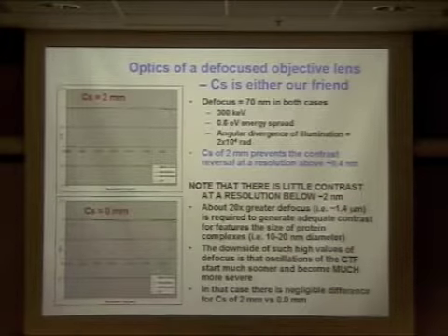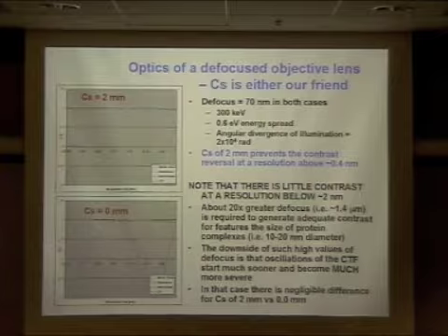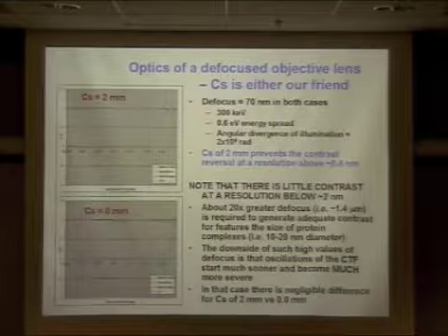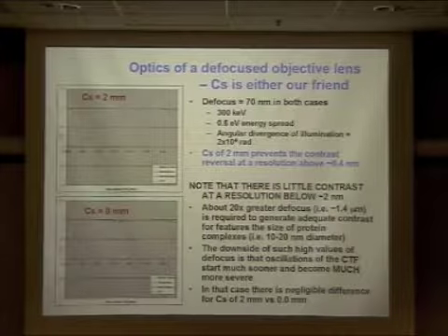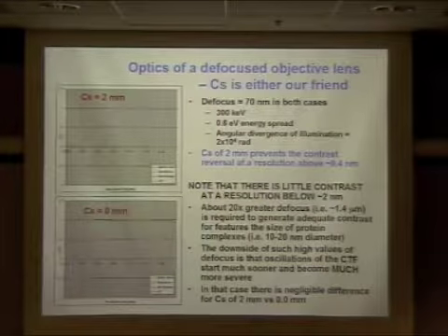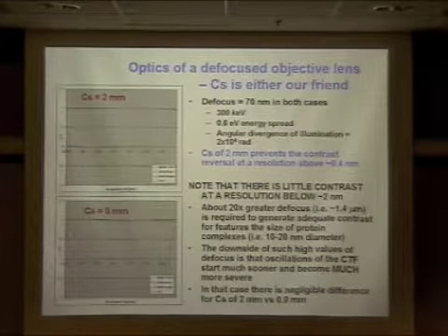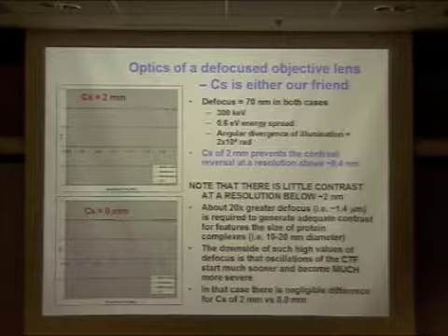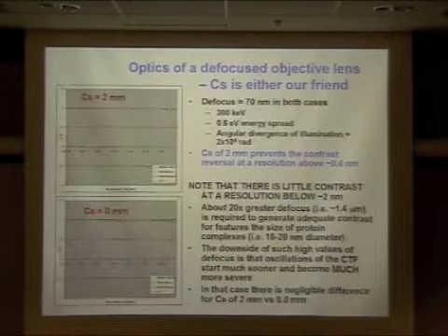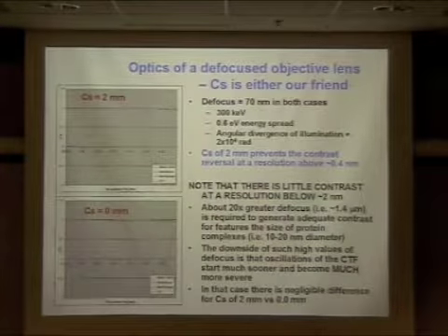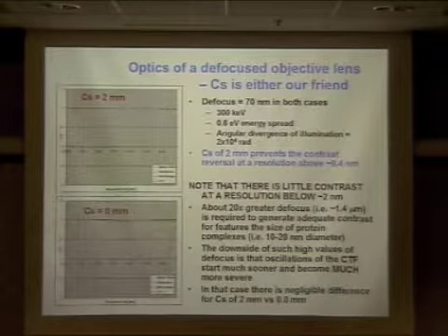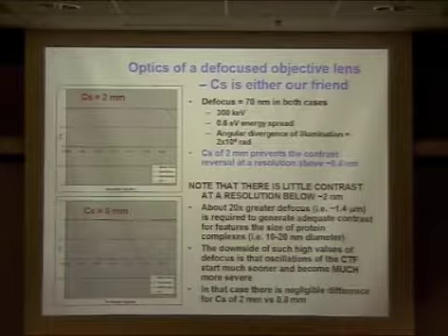A couple of nanometers. So you are able to do something similar to Scherzer focus, but with an additional parameter of Cs. So you can have 3 maxima instead of the 2 in the upper figure here with the Cs corrected microscope. So just adjust the defocus in such a way to optimize your imaging conditions.